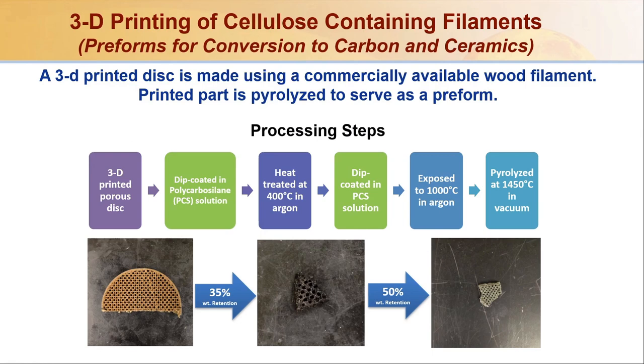From the bottom left corner, you start with a porous disc, which is wood color, and up to the pyrolysis it retains about 35% of the weight. Then we do another dip coating, pyrolysis and heat treatment, and it retains roughly half of the weight. So it's good for making porous structures, but at the same time you can also functionalize these and use them for different applications. I also want to let you know that the disc in the lower left corner is not the same disc that became the part in the right corner. There were different pieces, because we were cutting and characterizing them as well.